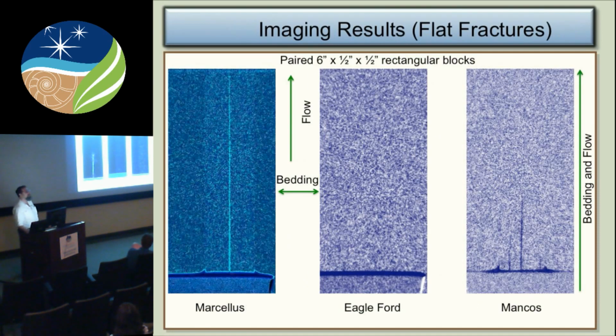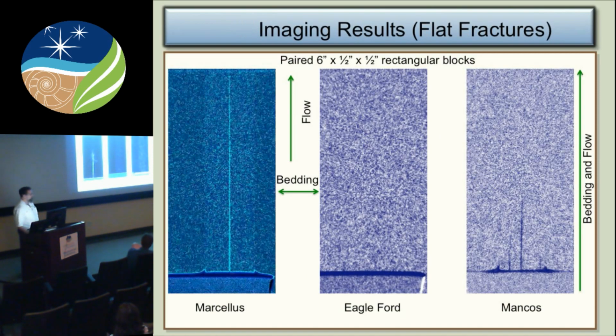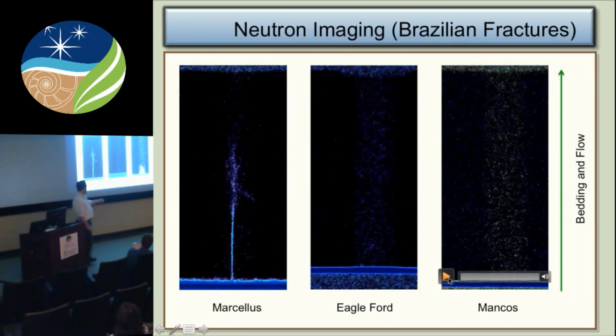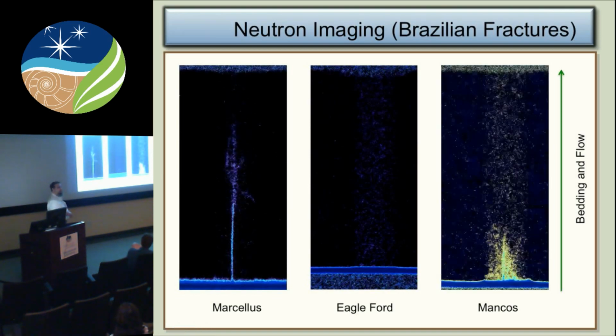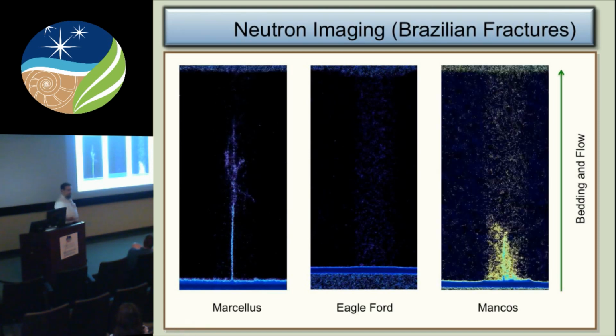Now, if we went, however, to real Brazilian fractures, the Marcellus again looks pretty similar to what you've seen before. You'll see that it comes up and then it hits a bunch of anastomosing fractures in the middle of the sample, so everything kind of slows down. But pretty much things are, and again now here bedding is in this direction. Pretty much things are pretty well confined to the fracture. However, look at the Mancos.